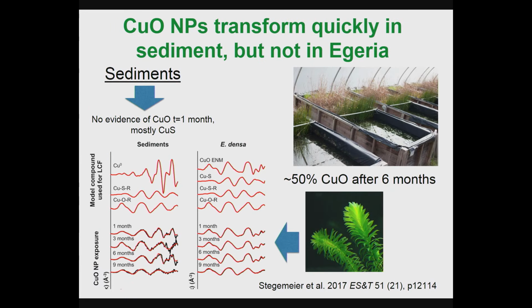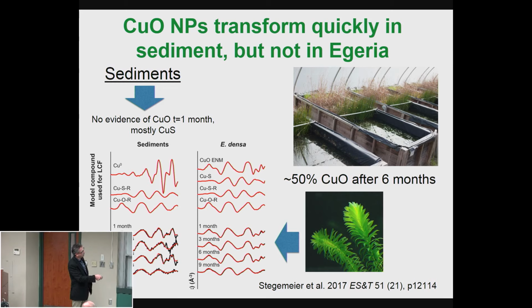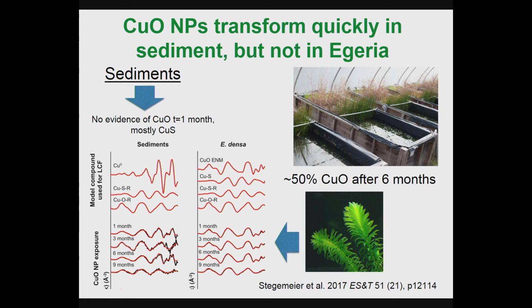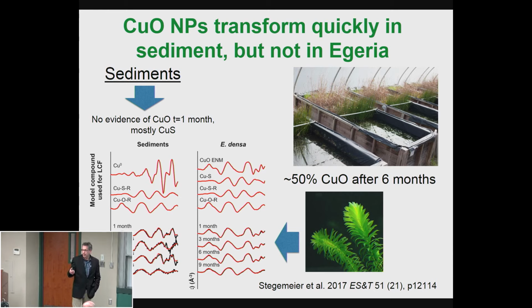So just to make a long story short, for the copper oxide nanoparticles we put in, if you look at the sediments, we basically took sediment out of the bottom of these tanks and we prepared them, we did X-ray absorption spectroscopy on it. Okay? And then what we found was, 1 month, 3 months, 6 months, and 9 months after we dosed, if you look at these squiggles, those squiggles look a lot like copper sulfide. And a lot of that material, even after 1 month, there was no copper oxide left at all. It had all transformed to copper sulfide. Okay? So that was almost expected, actually, because there's a fair amount of sulfur in these sediments, and you'd sort of expect that to happen.